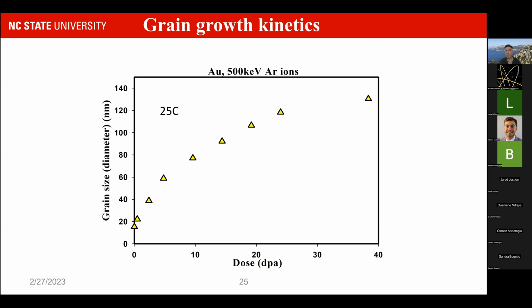The curves where we could do the kinetics information that I was talking about earlier. Again, here, thanks to this process of capturing pictures as the process happens, we are able to follow in detail the average grain size as a function of dose, and then we were able to fit it to this type of equation, where N and K are the fitting parameters.